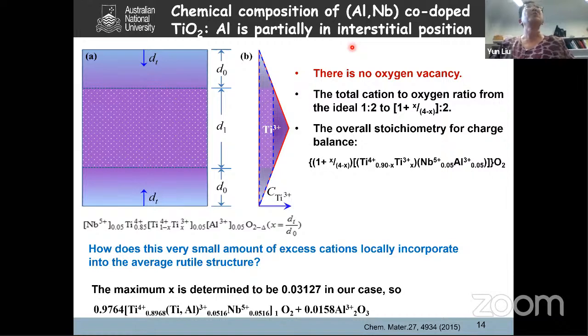For example, using aluminium, it's too small. So in that case, unlike indium, aluminium will partially go to the interstitial position, and you never observe any oxygen vacancy in these materials. Okay. So that's the complexity of this co-doping with at least one difficult to dope ion.